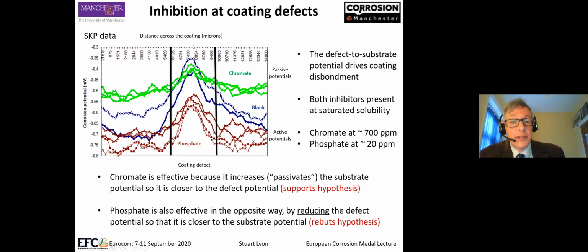We drilled, or laser ablated, a defect in the coating at this location here, and we ran the Kelvin probe over it after exposure. And we found that in the chromate case, well, in all cases in fact, the potential at the defect was elevated, which, if you go back to the cyclic potential experiments I showed you a few slides back, makes sense, because effectively the exposed surface becomes passivated in the atmosphere by atmospheric oxygen.